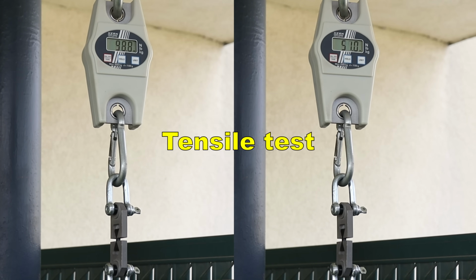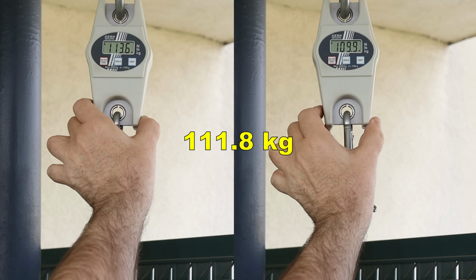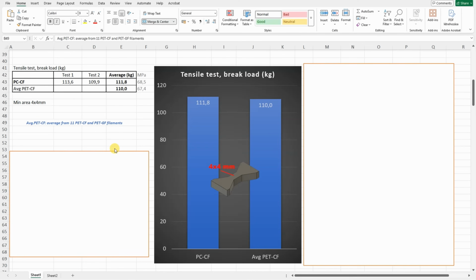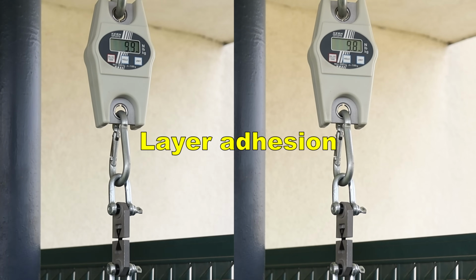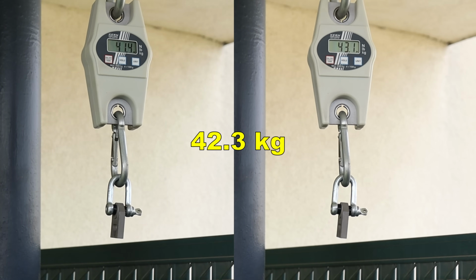Tensile test with horizontally printed objects. Quite strong. For the comparison, I will use the average PET-CF or GF, and I have 11 in that Patreon summary table. And this is quite a strong filament. I mean, anything above 100 kg tensile strength is good, and it is very similar in this case to the average PET-CF.